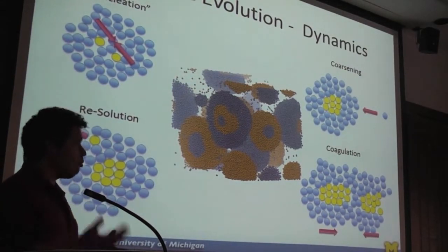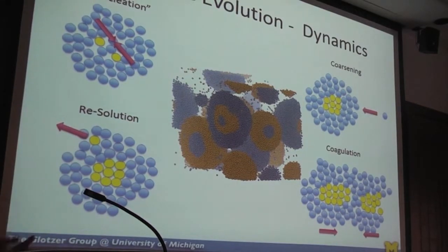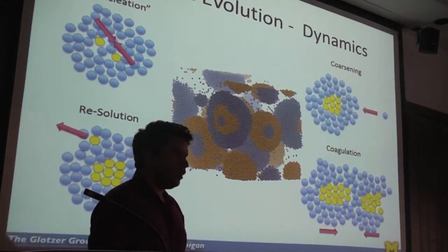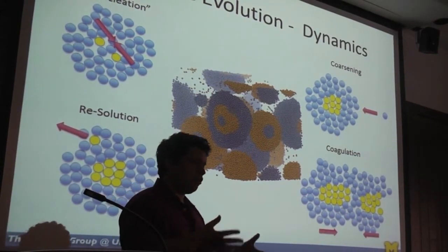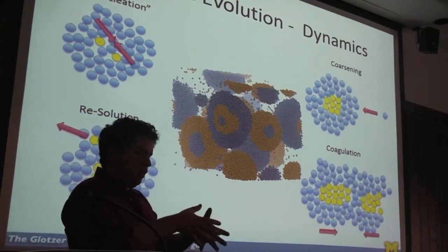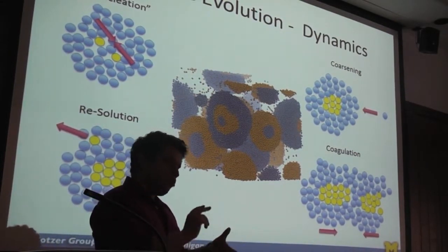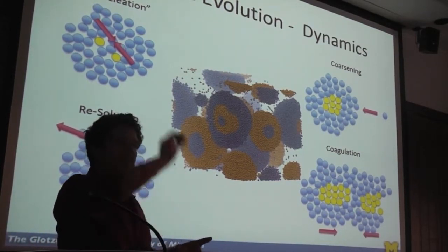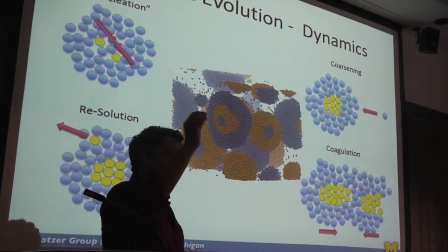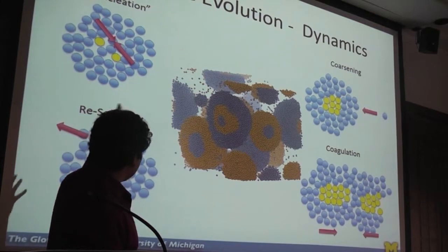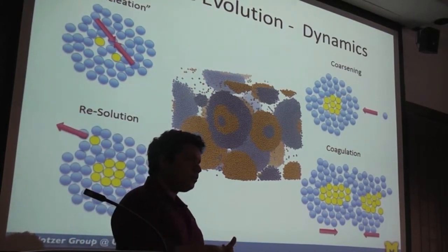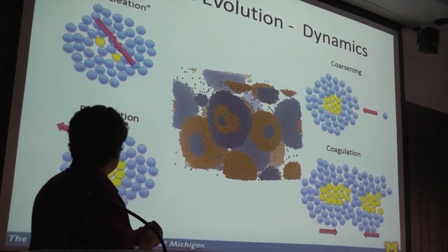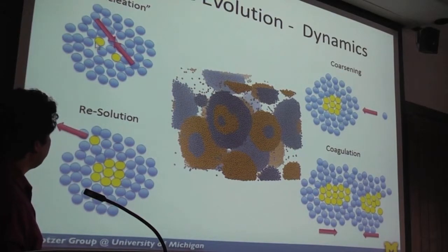And what is happening, the way that this system is evolving, is that particles are coming together. They're phase separating like normal, and they're making aggregates. As the aggregate grows, particles within them are switching to the opposite type, and they're trying to diffuse to the edge, and then go around and find another group of particles, another aggregate that they like to be with. As these aggregates get bigger and bigger, other particles start switching, and they have a probability of finding themselves together and nucleating a new layer.